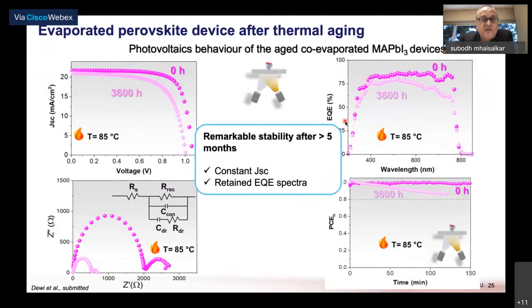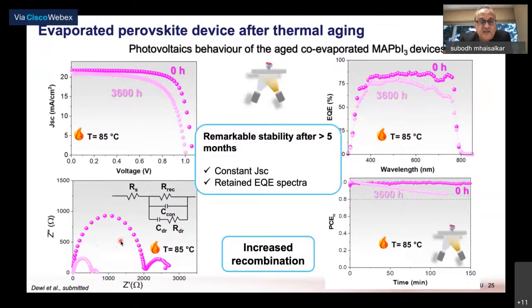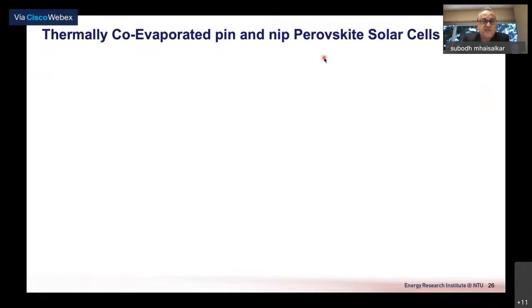We also took a slightly closer look at comparing these devices from a JSC perspective. From an EQE perspective, you can see that there really isn't any significant change. There is a slight degradation, but more or less the performance of these devices speaks for itself. There, however, clearly, as you can see from the impedance analysis, there is increased recombination. We also looked at these devices in terms of MPPT tracking, and even after 3,600 hours of exposure to high temperature, the MPPT performance over hundreds of minutes wasn't too bad. So the main takeaway message is there are significant differences in the stability of evaporated devices as opposed to devices which are solution processed.